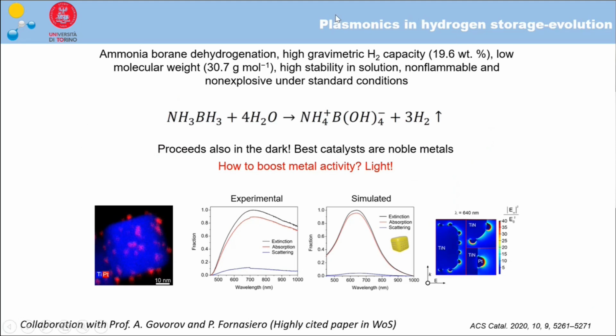In this case, we use plasmonic nanocubes made of titanium nitride, which is an alternative plasmonic material with properties similar to gold. You can see the absorption spectrum is centered around 600 to 700 nanometers. So the appearance of titanium nitride is similar to gold. Indeed, if you think, for example, of drill bits or many roofs of Orthodox churches, they look golden, but they are not covered by gold.